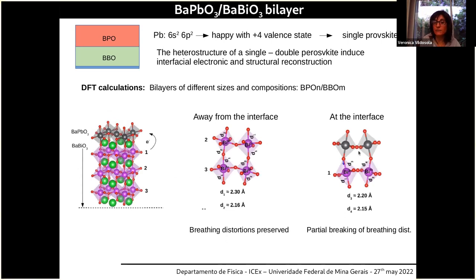So we calculated for these different sizes of slabs, and here you can see half of a unit cell, and this would be the interface of BPO with BBO. And what we observe is that there is a charge transfer between the two materials.